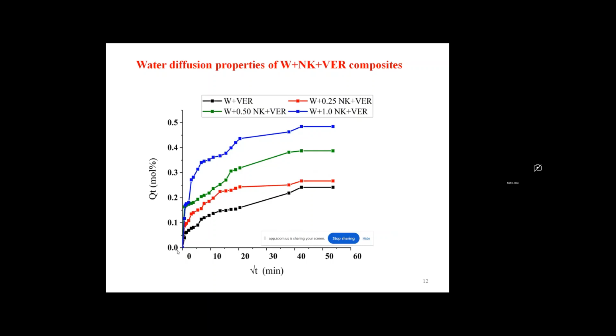Now, I have also analyzed the water diffusion properties. So here you can see the least water diffusion was found with the neat composites, without adding any nano kaolinite. And as the nano kaolinite concentration is increased, the water diffusion is also showing a positive trend.